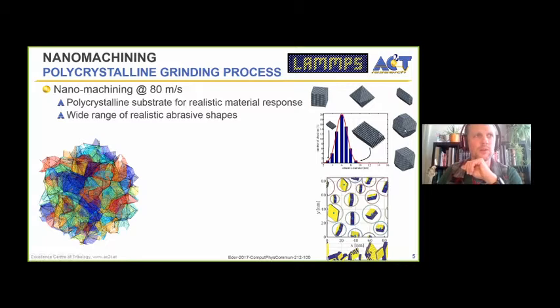You can get more spherical ones like these truncated octahedra or these cubo-octahedral, but you can go, let's say, full parameterization into plate-like particles, rod-like particles. However, these still have a cubic lattice. These down here are more recent. Those are actually alumina, chemically, and let's say from the shape.